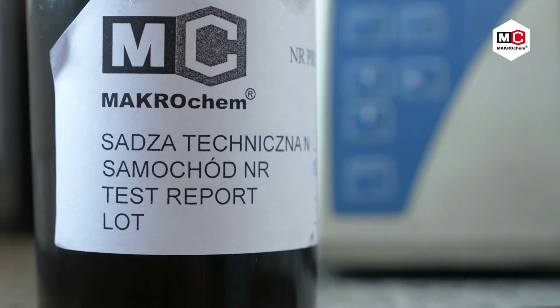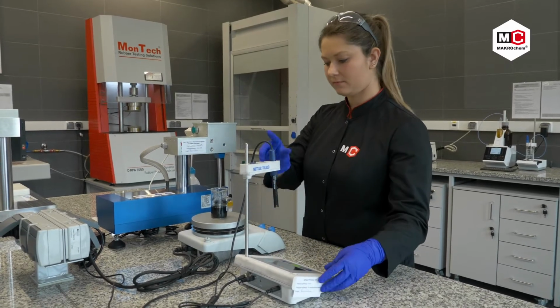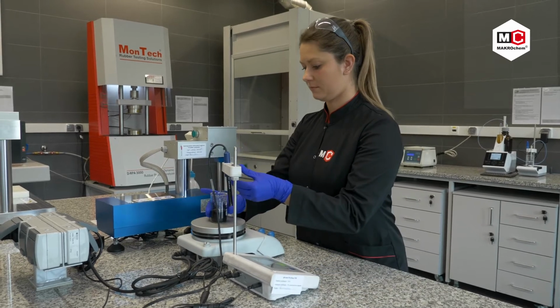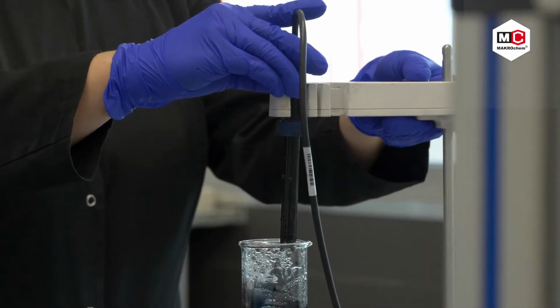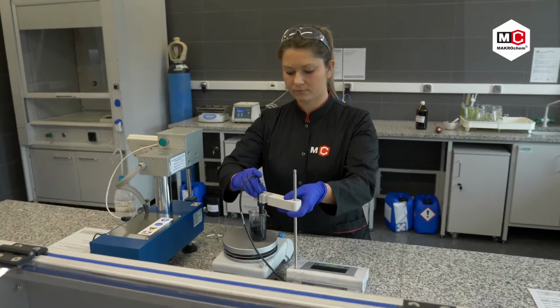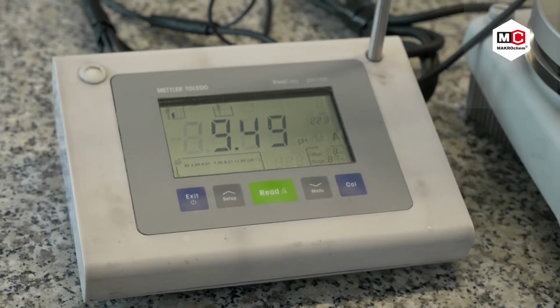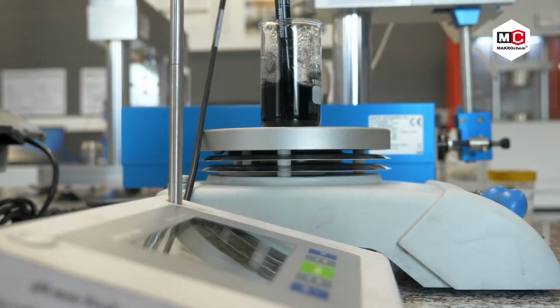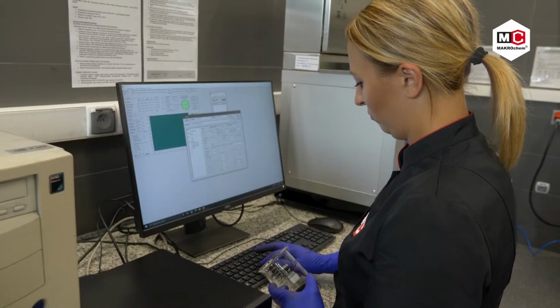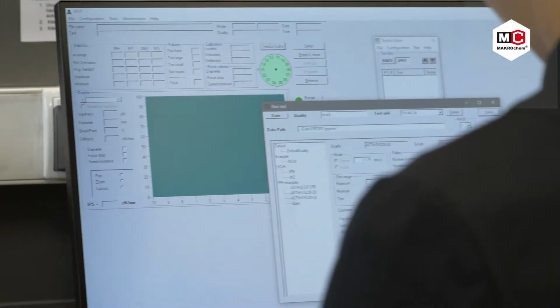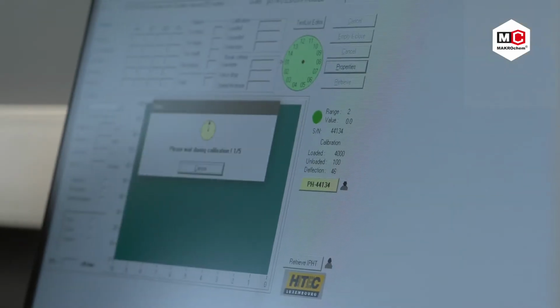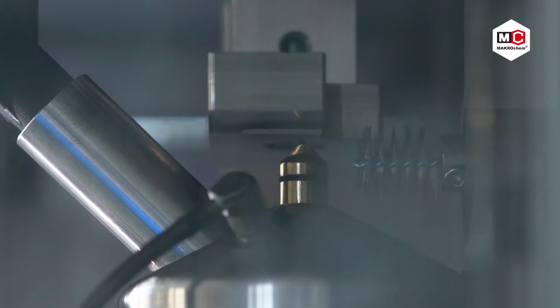Next, we measure other values important in the production of rubber composites. One of them is the pH level of water-based dispersion. It describes the bulk of acid groups of carbon black, which will significantly influence the speed of vulcanization of rubber compounds. As commercially available carbon black is pelletized, we measure pellet hardness. If those values are in proper range, transportation and seamless work of industrial installations is secured.